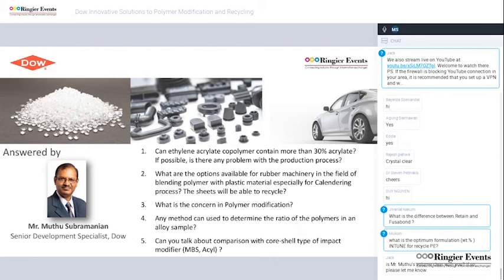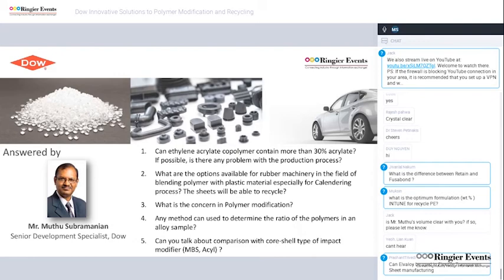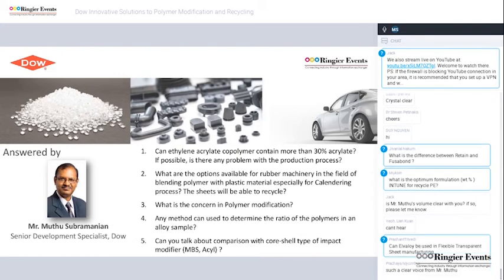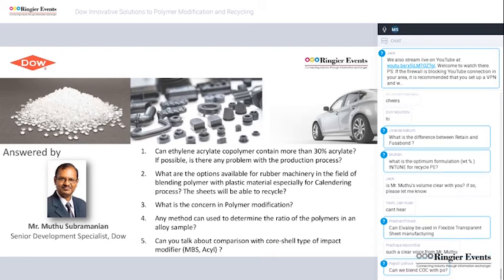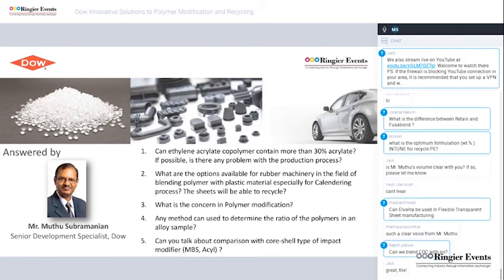And the third question is, what is the concern in polymer modification? So in this presentation, we have shown the data and discussed our modifiers, how they are compatibilizing and act as a coupling agent with the mineral fillers to improve the impact, as well as the processability of engineering plastics. And for high heat resistance engineering plastics, for example PPS, there is a concern whether adding modifier will cause a reduction in the heat resistance performance. So for PPS, we can add a blend of modifiers, like we can add our Surlyn and a GMA-containing polymer, the terpolymer, which is our Elvaloy PTW. Since this blend will react with the PPS, it can cross-link with the PPS. Because of that, it can improve the heat resistance as well as the toughness.